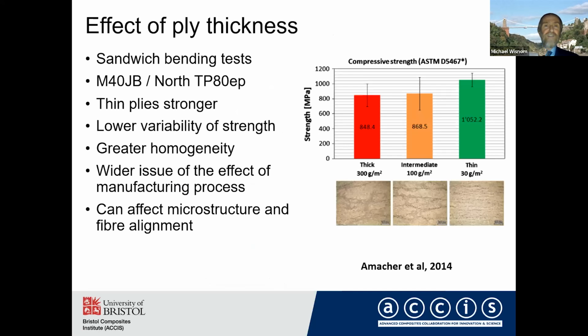The effective ply thickness is another thing which makes a difference. You can see these tests here done at EPFL with different thickness plies. The very thin ones, down to 30 grams per square meter, are significantly stronger and also have lower variability in strength. This is because there's greater homogeneity. In those micrographs, you can see that the one with the thin plies on the right is much more homogeneous. With the thicker plies, you see more resin-rich regions between tows. This shows a more general issue, which is that the manufacturing process may affect the distribution of fibers, the microstructure, fiber alignment, and hence potentially the compressive strength.